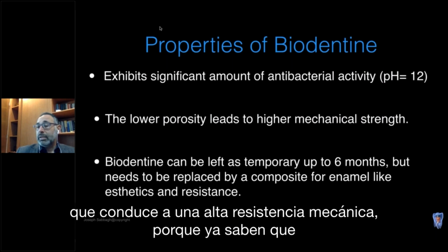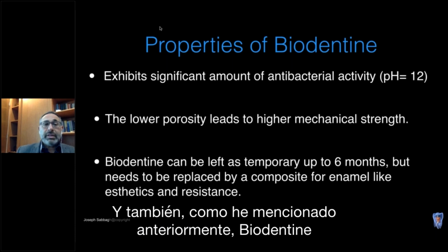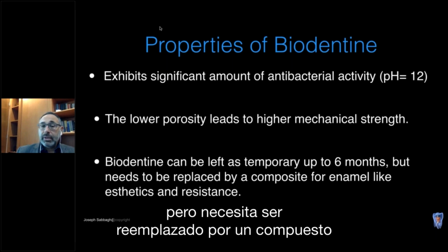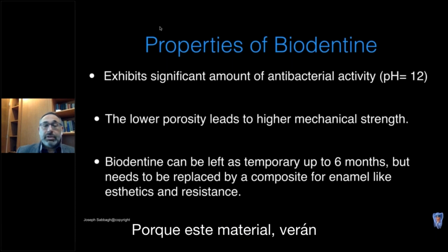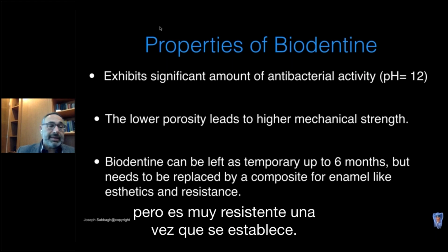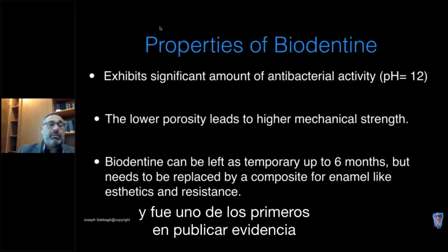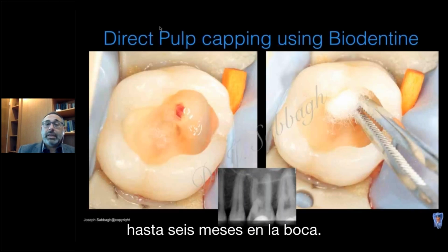And also, as I mentioned, Biodentine can be left as a temporary up to 6 months, but needs to be replaced by a composite for enamel-like aesthetics and resistance. Because this material, you will see that it has a chalky color, but it is very resistant once it's set. And I think that Professor Colon did a lot of investigation about this, and he was one of the first to publish evidence that this material can last for up to 6 months in the mouth.